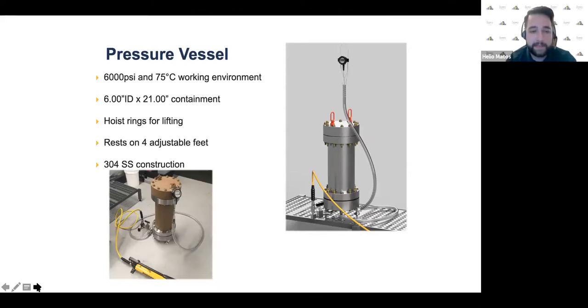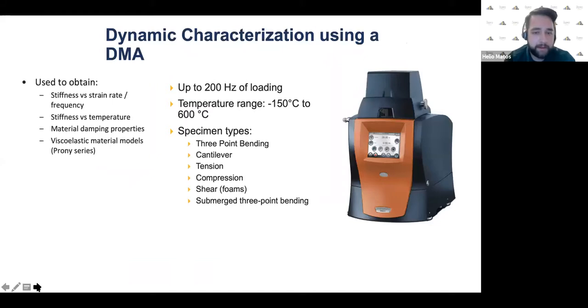And in the next slide, we have another piece of equipment that was added recently to the lab, which is a dynamic mechanical analysis machine called DMA. So we can do material characterization between negative 150 C and 600 C. Also, the loading rate is up to 200 hertz. And what that would translate to in terms of strain rate depends on the geometry of the material. But we essentially can do a strain rate sweep.